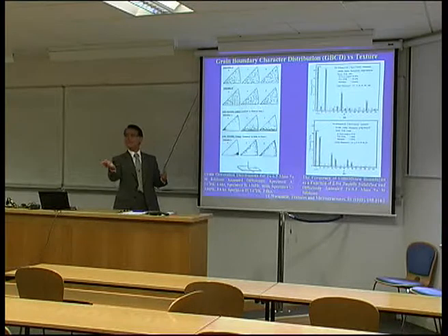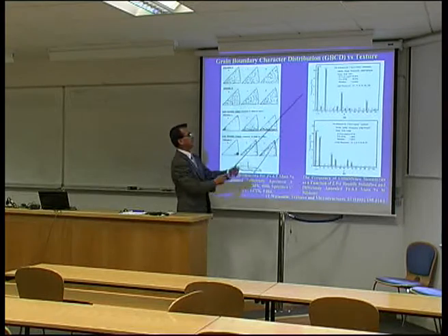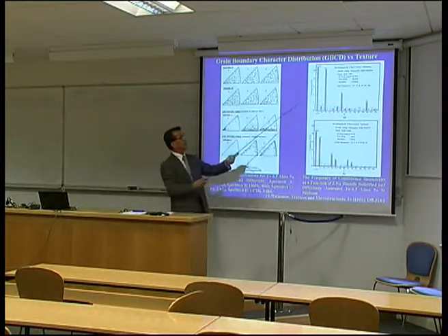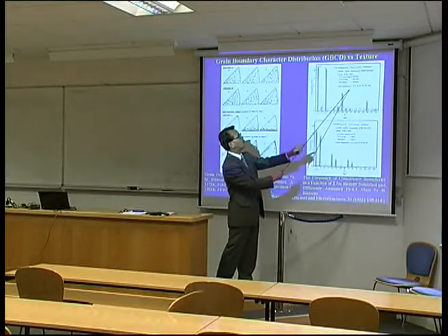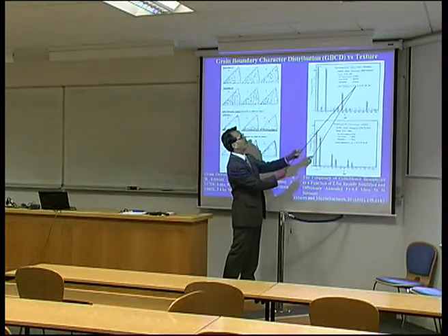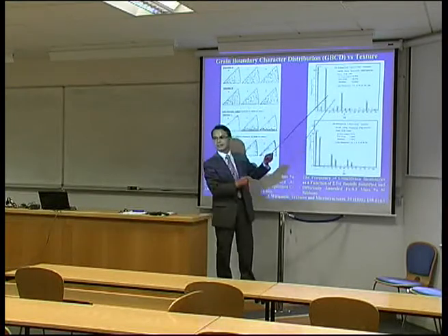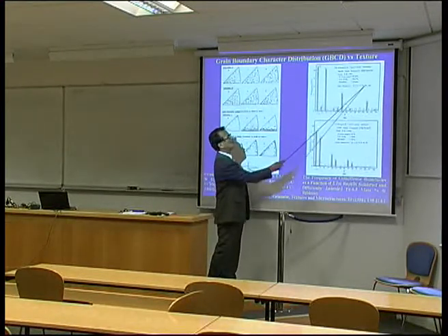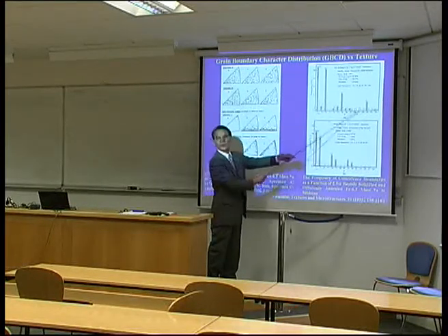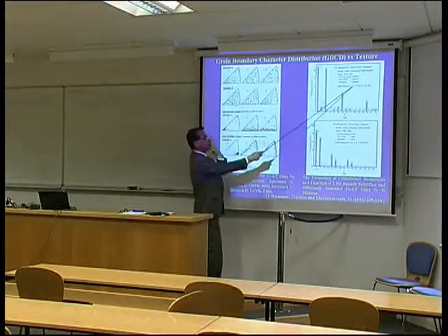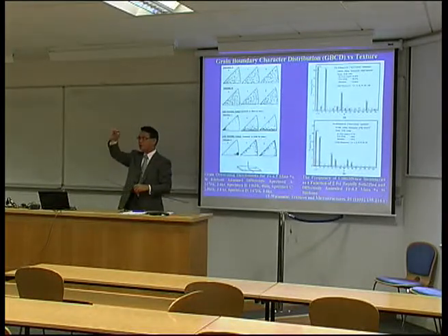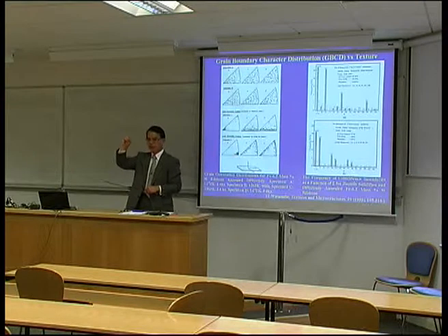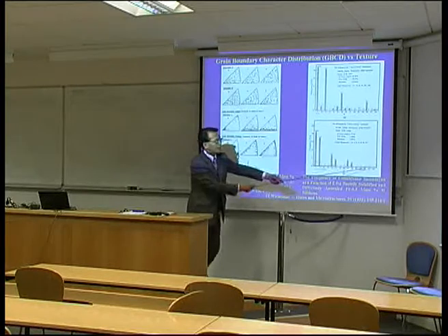In this case, as you know, iron silicon has the BCC structure. From the coincidence site lattice theory of grain boundary structure, we can predict like this: for the 1-0-0 rotation axis, from the lower sigma boundaries, 1, 5, 13, in this order. So exactly as we expect from this order, this is okay. This means low sigma value, as I mentioned last time, the degree of order depends on the sigma value. So low sigma value corresponds to a high order of the atomistic structure. So as you expected, exactly like this.